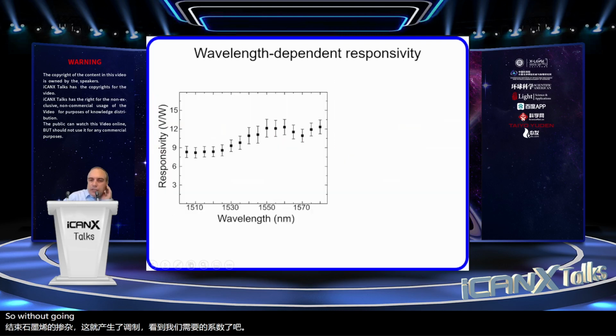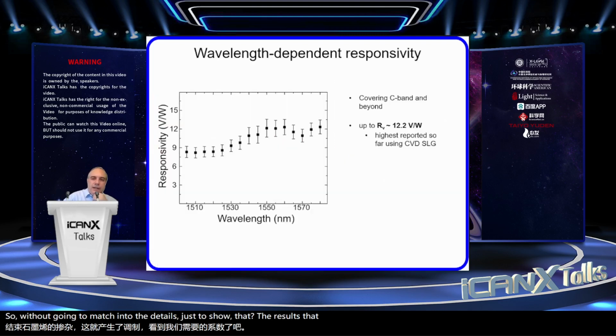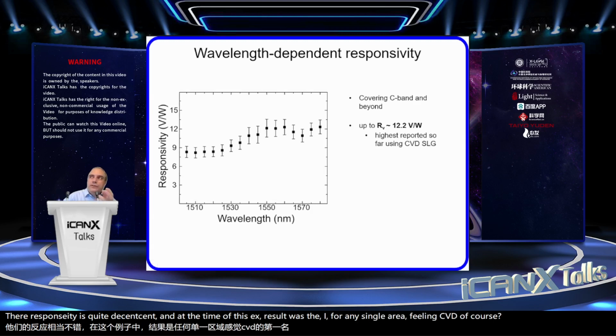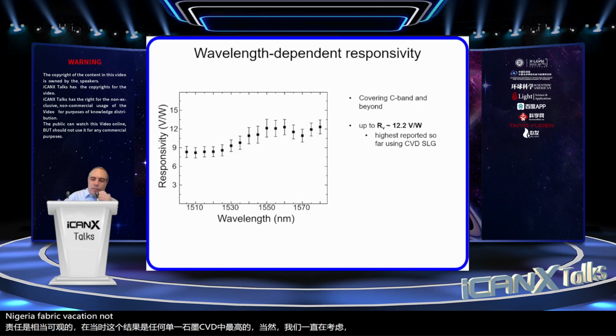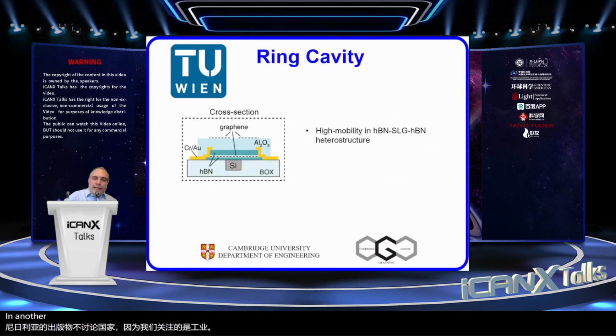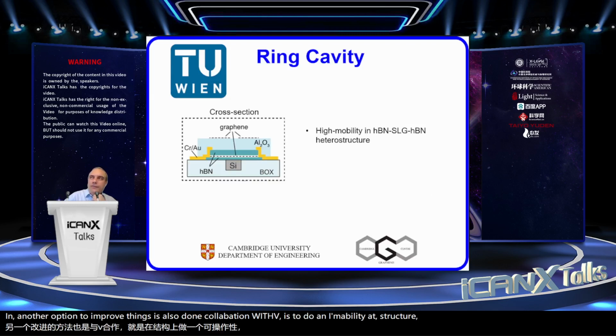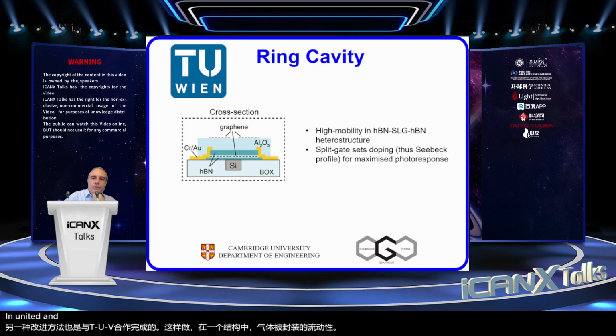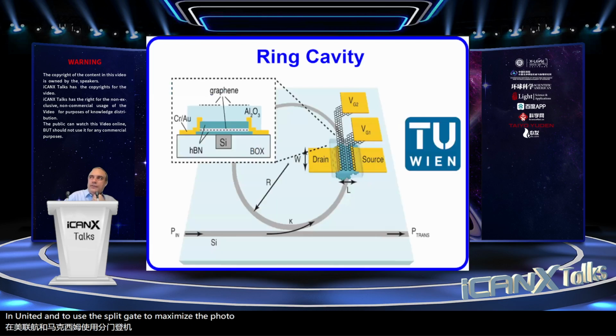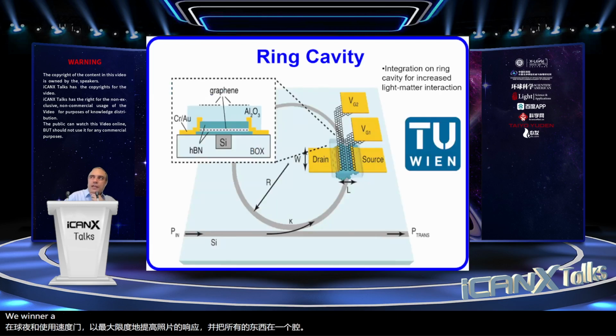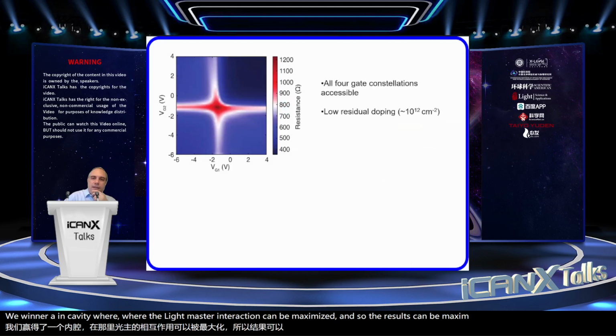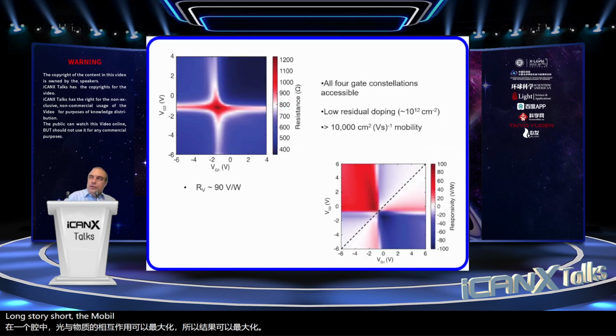So without going too much into the details, just to show that the device works, the responsivity is quite decent, and at the time of this result was the highest for any single layer graphene CVD. Of course, we are always considering large area fabrication, not the Scotch tape, because we look at the industry. Another option to improve things, also done in collaboration with TU Wien, is to do a high mobility heterostructure where graphene is encapsulated in boron nitride, and to use the split gate to maximize the photo response and put everything in a ring cavity where the light matter interaction can be maximized, and so the results can be maximized. Long story short, the mobility is very good in the samples, over 10,000.